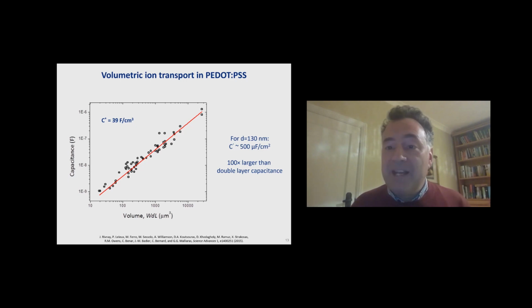So a magical material, you just put a wafer thin coating on your electrode and you have enhanced communication with the brain 100-fold. This means that now you can make small contacts, you can make 100 times smaller electrodes and still be able to record with the same accuracy, with the same signal to noise ratio as a much, much larger gold electrode or platinum electrode. So you just gained in spatial resolution.